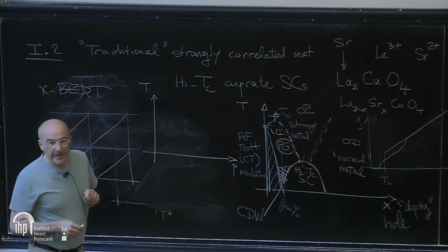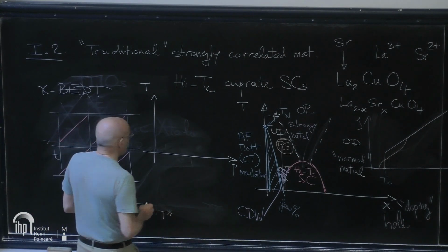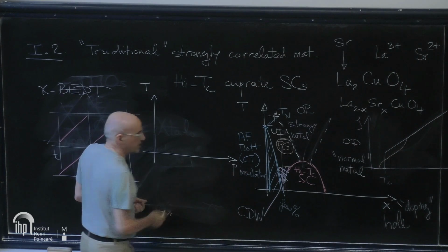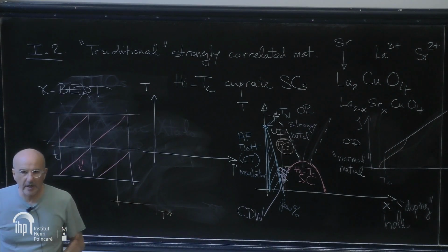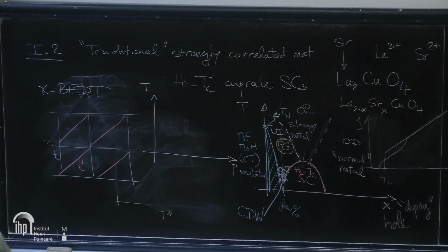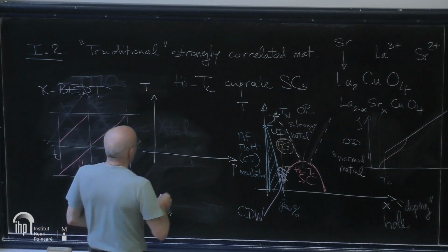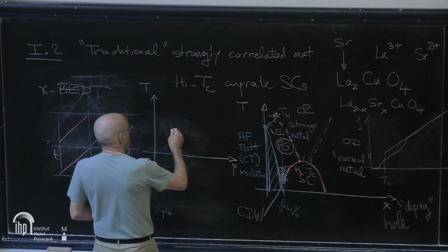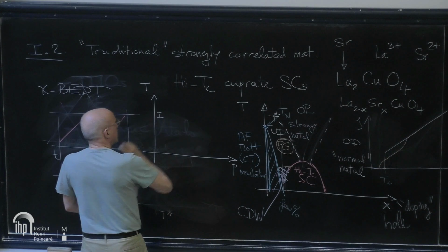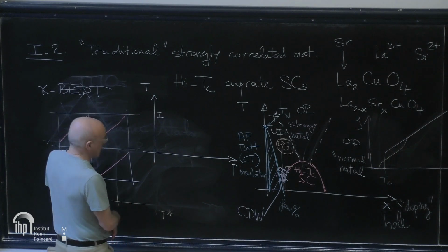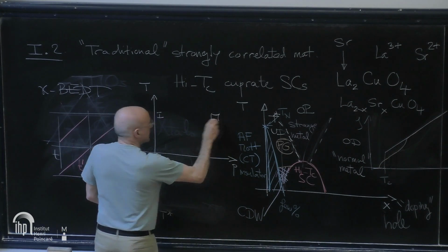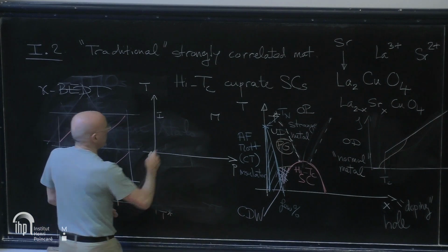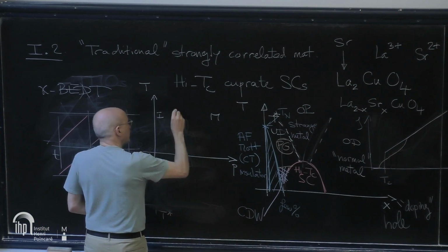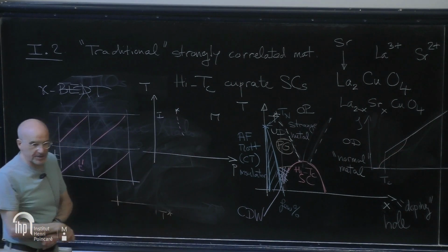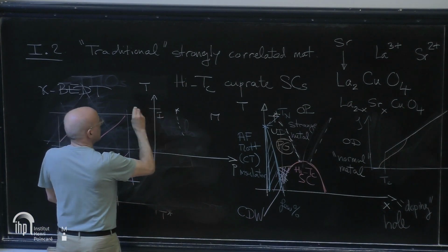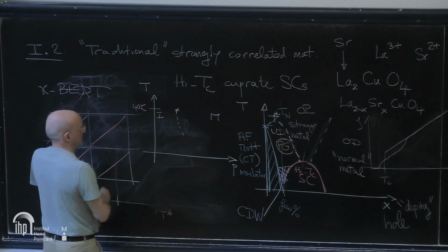The undoped material displays the following phenomenology. Pressure brings the molecules closer to one another, hence the bandwidth larger. And what happens is that there is a Mott insulating state at low pressure. There is a metallic state at high pressure. In between, there is a first-order phase transition, like a liquid-gas transition, that separates the two. This scale is about 40 Kelvin.